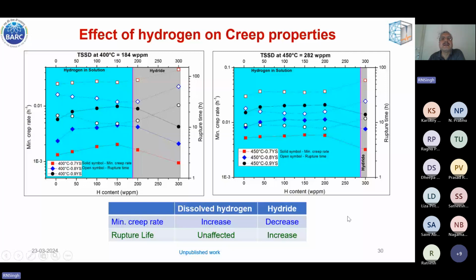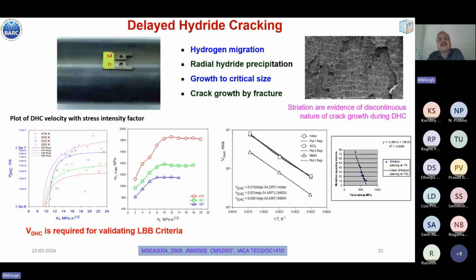Now coming to delayed hydride cracking, it is caused by hydrogen migration up the hydrostatic stress gradient. Near the crack tip, hydride precipitation takes place. For pressure tube material, this hydride precipitation has a radial orientation. This radial hydride grows to a critical size, and once it attains the critical size, it fractures and growth of the crack takes place. And this whole process repeats, and the cracking of hydride is delayed by the time required for hydrogen to diffuse to the crack tip and form a hydride of critical size, and that's why it is called delayed hydride cracking. The evidence for this comes from the fracture surface also.